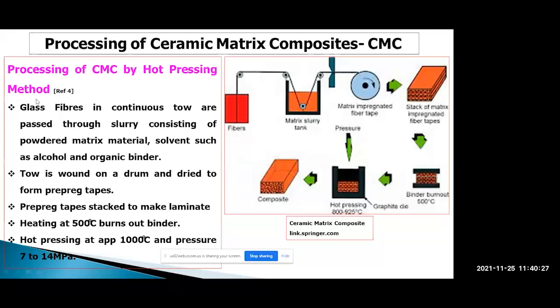Just one typical method I am showing: processing of CMC by the hot pressing method. These are the fibers taken and impregnated in the matrix slurry. Solvents and binders are also there in the slurry. Then they will be collected and wound on a drum, and cut in tape form. This stack of matrix-impregnated fiber tapes has to have the binder removed, that is, burnout at 500 degrees. Then again, it is pressed under very high pressure, and the temperature is more than for MMC. It is almost 1000 degrees, and a pressure of 7 to 14 MPa has to be applied. So this is the component.